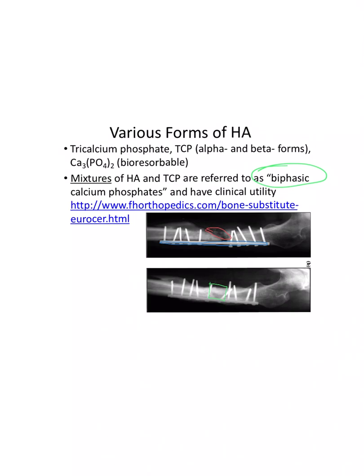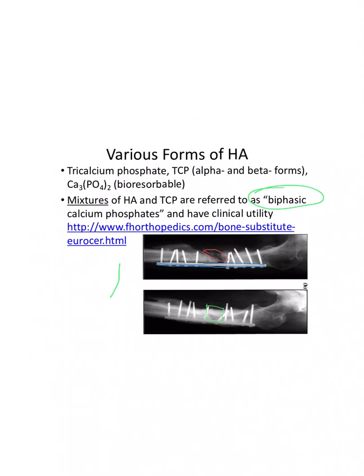All right, any questions about that? And so again, this is tricalcium phosphate. There are alpha and beta forms. The alpha form is preferred, and it's considered bioresorbable more quickly than HA, but you don't make it out of pure TCP. It's still a lot of HA in there as well. So it's the right moderate amount of these two phases.